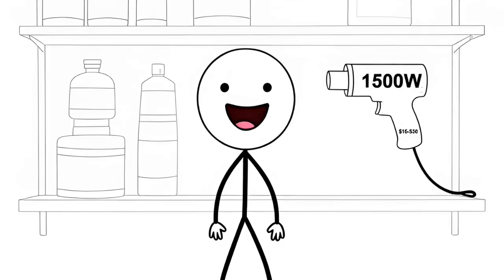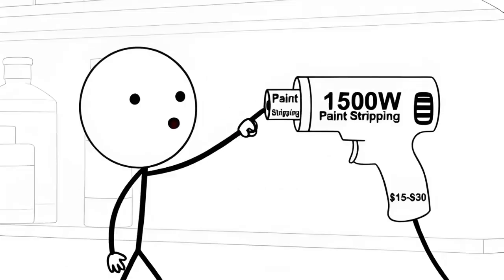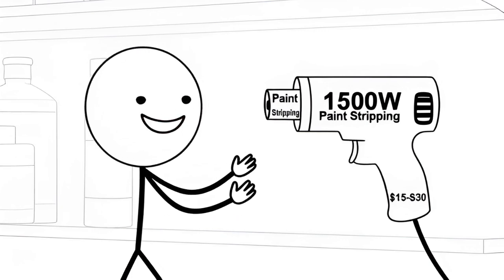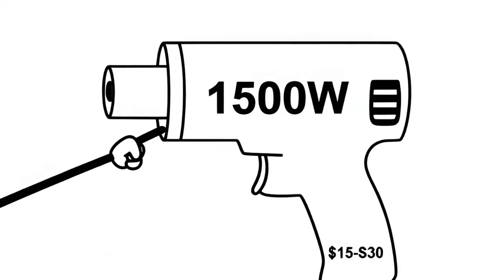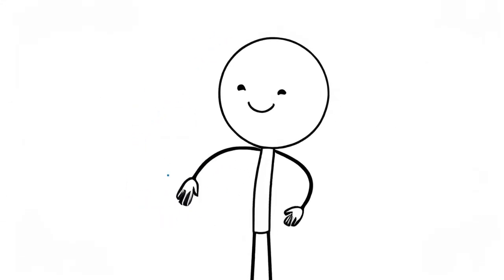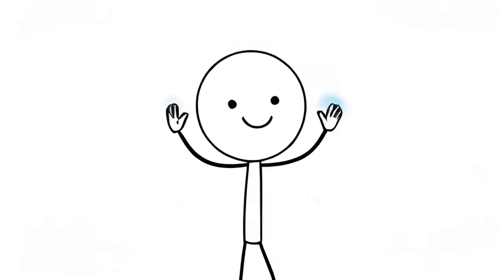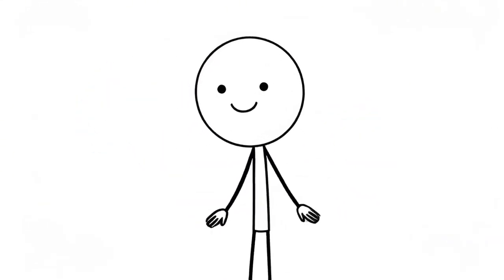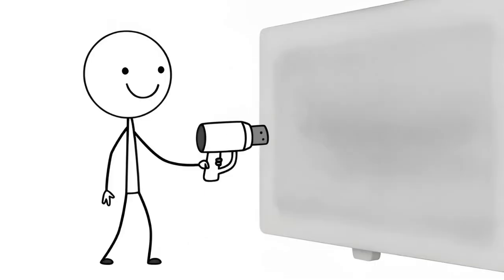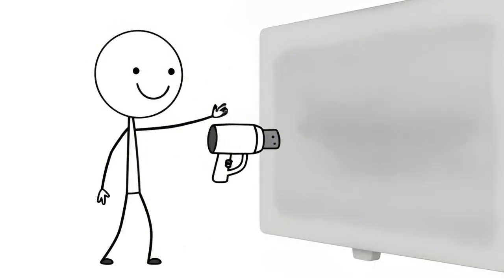Buy a heat gun rated for at least 1500 watts from any hardware store. Models designed for paint stripping work perfectly and cost between $15 and $30. Clean the faded plastic trim thoroughly with soap and water to remove surface dirt and any existing dressing products. Dry completely. Set the heat gun to medium heat, approximately 400 to 500 degrees Fahrenheit. Hold the nozzle 3 to 4 inches from the plastic surface. Move the heat gun slowly across the faded area using smooth overlapping passes.